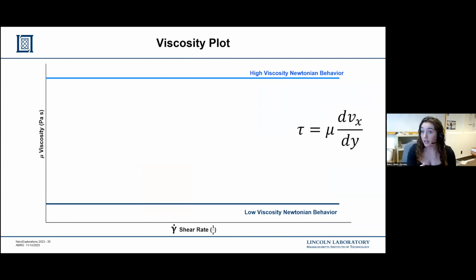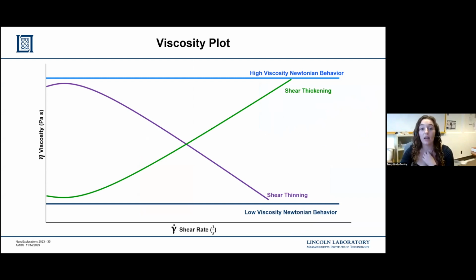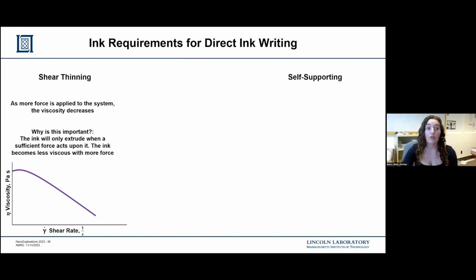so it can calculate out and produce a plot that is viscosity on the y-axis. So when you have your Newtonian behaving fluids, it's this horizontal line. When you add shear stress, shear thickening and shear thinning, you get these two curves. Remember, we want our inks to be shear thinning, which means when a force is applied to the system, the viscosity decreases. And this is important because we only want our inks to extrude when a sufficient enough force acts upon them. The second thing that our inks need to be is self-supporting.